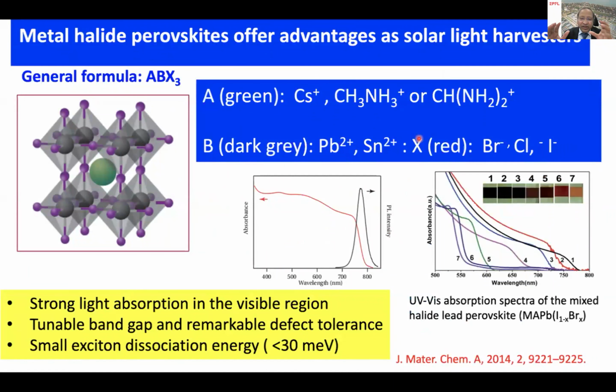The perovskite materials are like a battery materials, very simple composition. You have a salt-like material, that's ABX3, where A is a monocation that can be inorganic cesium or methylammonium or formamidinium. The B is a metal. In this case, we are discussing only lead 2+, and X is a halide, which can be bromide, chloride, and iodide. And in my talk, I will be focusing only on iodide, and the bromide and chloride have applications in the light emitting diodes.